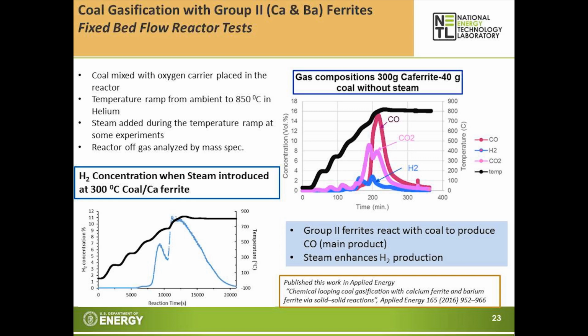We measured the reactor effluent gas concentrations using a mass spectrometer. Okay, these are the gas compositions when we had calcium ferrite and coal, and did the temperature ramp, and this is without steam. As you can see, CO is the main product that's formed during the ramp. So the calcium ferrite reacts with coal to produce mainly carbon monoxide. And when we did the temperature ramp in the presence of steam, the main product was hydrogen.